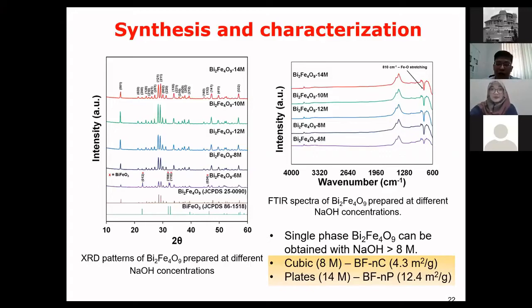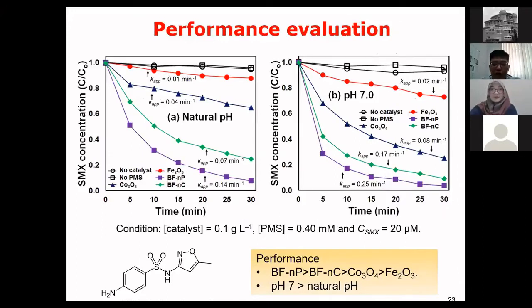And the most important thing, of course, is whether it's applicable or not. We test it for removing sulfamethoxazole, and we get a very good result. We can see that at natural pH, at pH 7, at pH 11, this catalyst is very durable. So this catalyst, for us, we consider as one of the best catalysts for PMS activation.